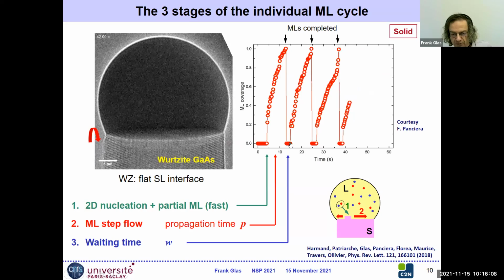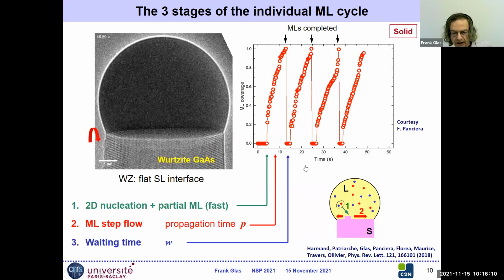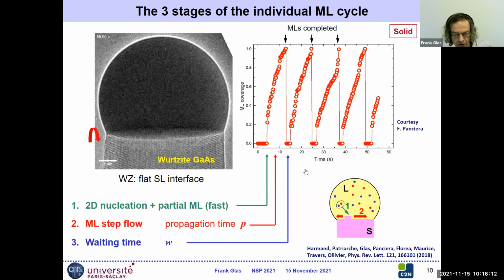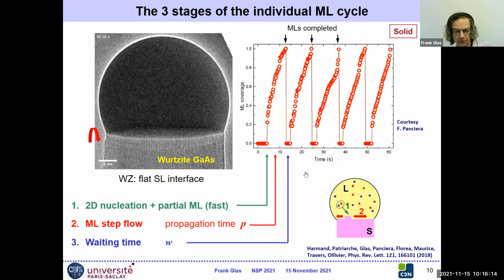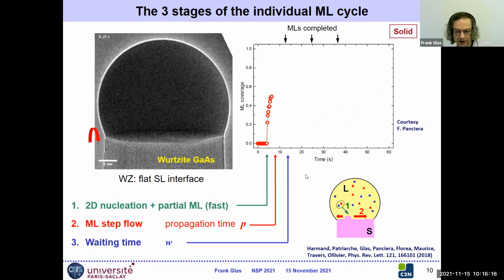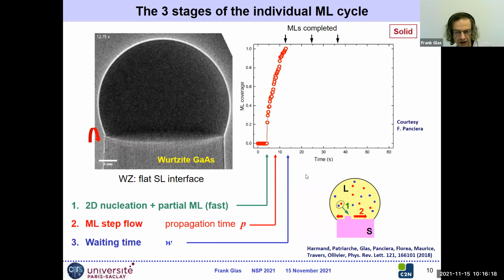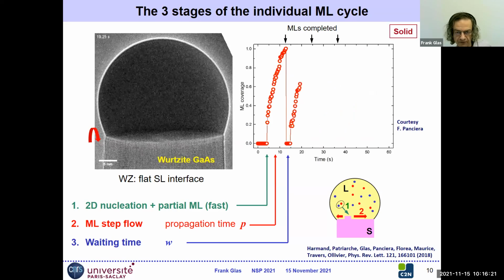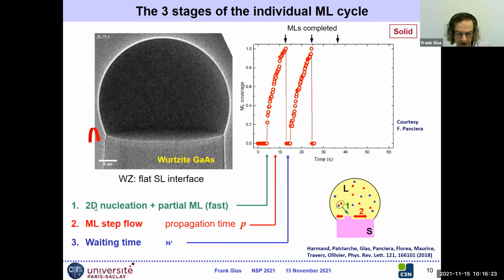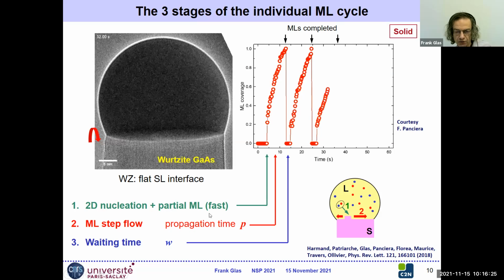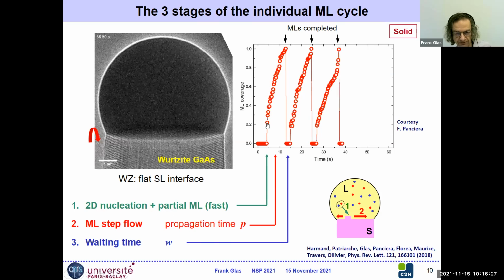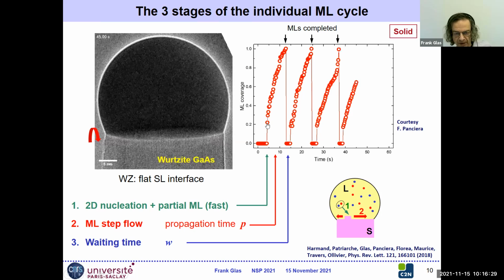Then we have to wait for some time to have a new nucleation. So we don't have two stages as believed initially in the formation of each monolayer, which would be nucleation and formation of a full monolayer followed by waiting time. In fact, we have 3 stages. We have nucleation and very fast formation of a partial monolayer.